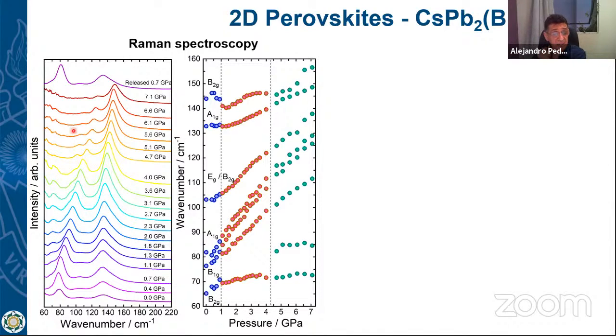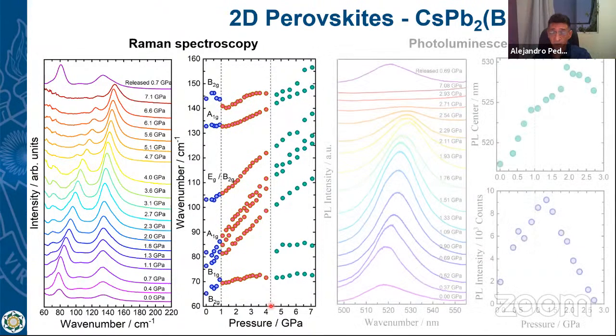And an interesting thing is when we release the pressure, the structure is recovered. So it is an irreversible transition. And when we study the phonons, you can see how the phonons are changing, suggesting that there is a couple of phase transitions, one at 1 GPa and around 4.3 GPa.